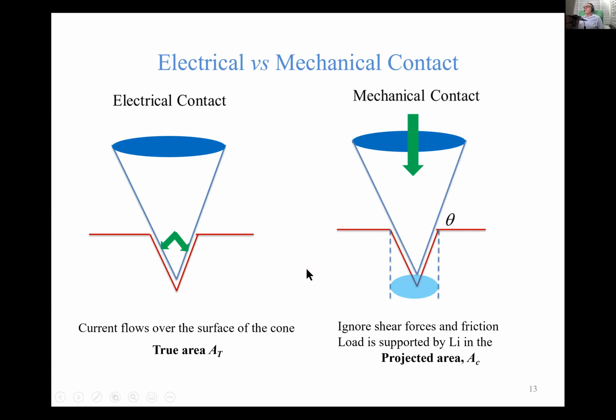But mechanical contact is different. In mechanical contact, the load is going to be supported by the lithium in this projected area. And so if you think about hardness, this is the principle behind measuring hardness. You're dividing the load by the projected contact area. Now, of course, these contact areas are related, and for any given surface, you might have something like the mean, the average of the mean cosine angle or something that might be more complex. But in general, these numbers are proportional to each other, but they're not the same thing.